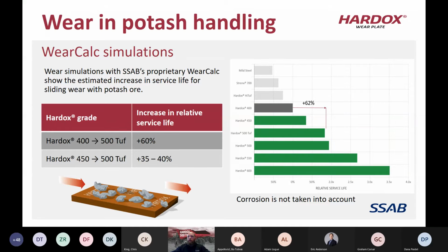So if we put this into relative terms, going from AR 400 up to a Hardox 500 Tough, you can see a little over 60% increase in service life. And even from a 450 Brinell steel to 500 Tough, you can see anywhere from 35 to 40% increase in service life.